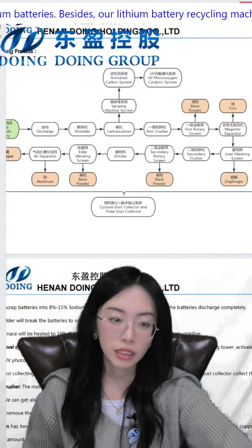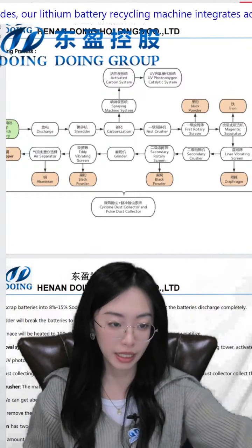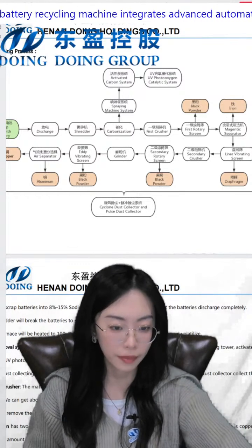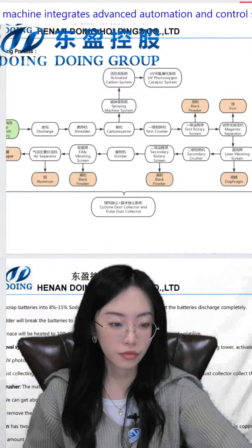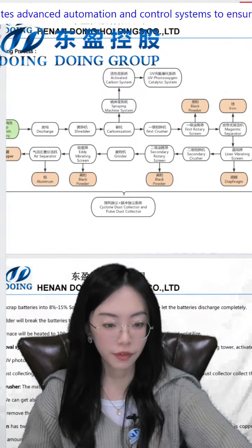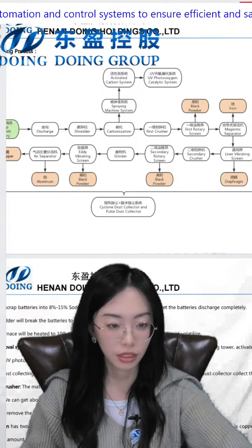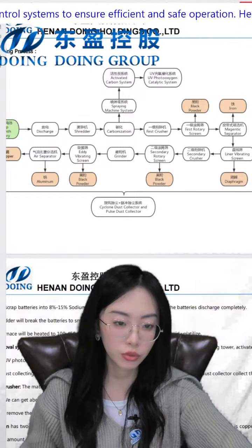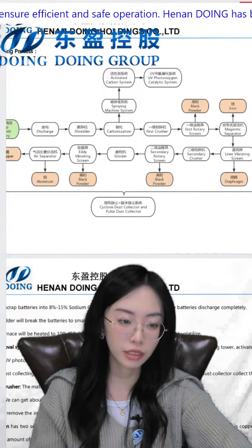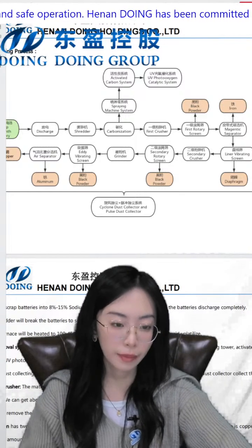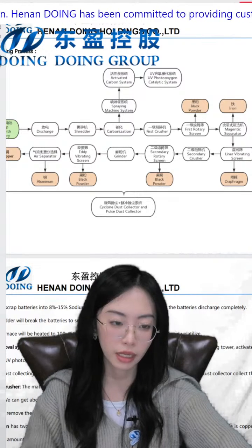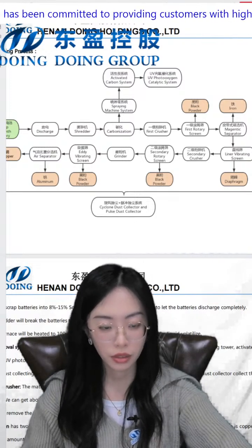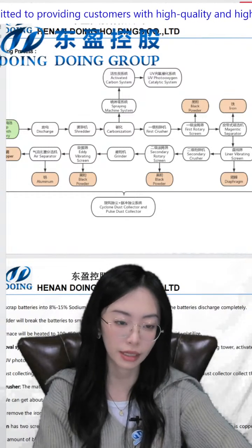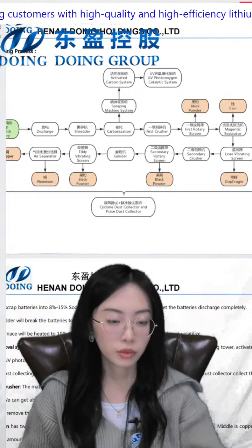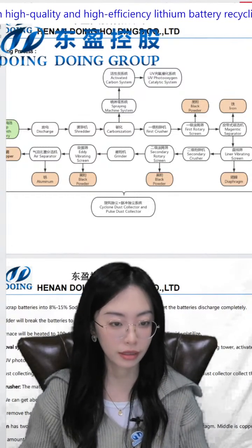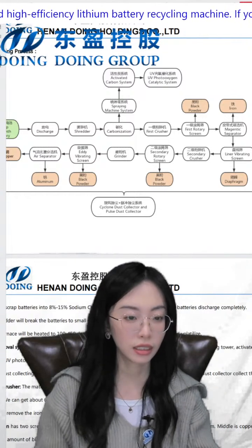And then the granular shaped aluminium and the copper will come to the ID vibrating screen. This is a high precision screen machine with low noise, high efficiency, and whole sealing structure. It is applicable to sieve granular powder materials. And in this step, the black powder recovery is about 99%. In this step, all the black powder we can recycle, and we can just load it directly or have a deep processing. Then, what products remain is the aluminium and the copper.